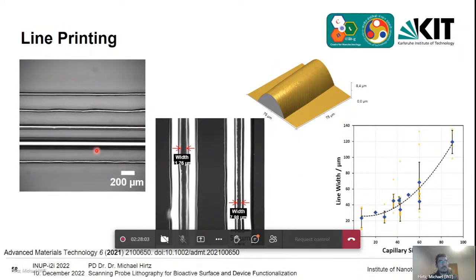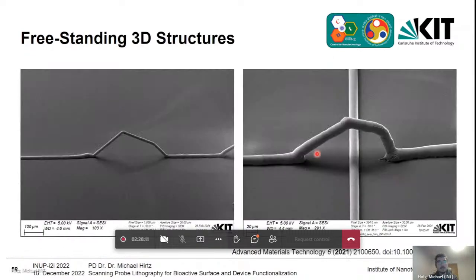So with this technology, we can now print different lines of this. And you can see the line width is correlated with the capillary size. And because of an oxide layer that is building around it, you can even have freestanding 3D structures. So it's a very nice, flexible material. This is still liquid and there's no curing required. But still, you can have things like this kind of intersects.